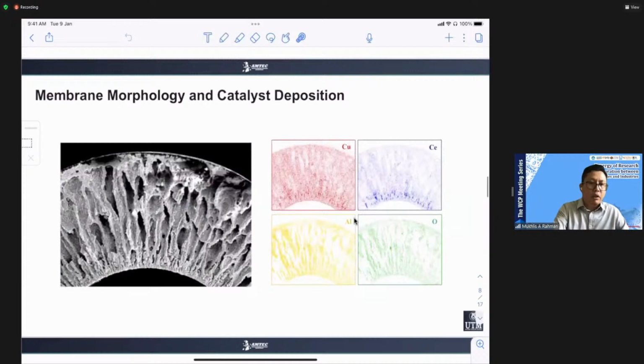This figure shows our ceramic membrane that we produce using the phase inversion and sintering technique. To tell you the truth, it's quite hard to get this structure. It really depends on the viscosity of the suspension. But if the correct viscosity is produced, we are able to get 80% finger-like structure over here. This is the place where we put the catalyst. The carving of this structure is caused by a phenomenon called viscous fingering during the spinning process.